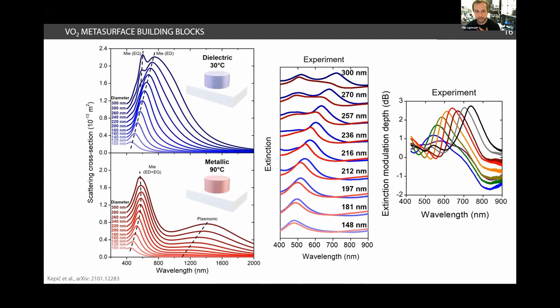Yeah so I have a question about the thickness of the VO2. So generally what's the thickness of VO2 you are using? Well yeah it of course depends on your applications. Usually it's tens or hundreds of nanometers. For example high tens like 80, 90, 100 nanometers for these resonators which should work in dielectric phase you need to have some sort of thickness in order to be able to excite also some higher order modes which are very interesting. So you go up to 200 or 300 nanometers in thickness. It all depends on your application of course. If you make it thicker your losses adapt and you get higher losses in transmission.